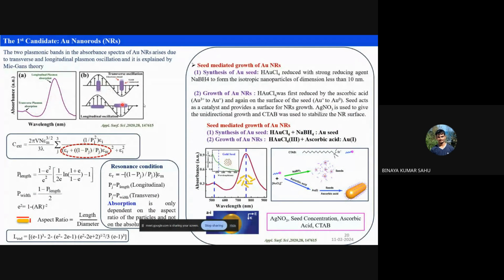For that, the technique we utilized is known as seed mediated growth. It is basically a two-step process. First, we prepared some seed by the interaction of HAuCl4 and NaBH4. Then later on, we made the reduction of HAuCl4 on that particular seed. You can understand from this diagram. In the first step, we created some seed, and in the second process, from the seed itself, you can grow different kinds of gold nanorods. So these are the different gold nanorods that have been created using this technique.